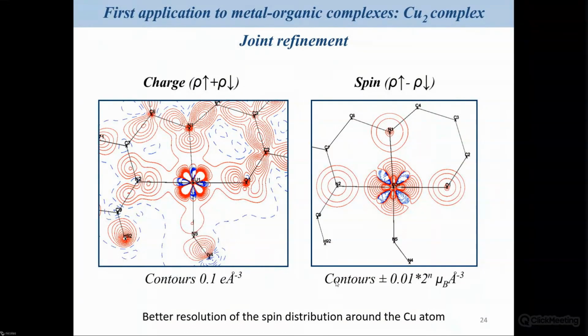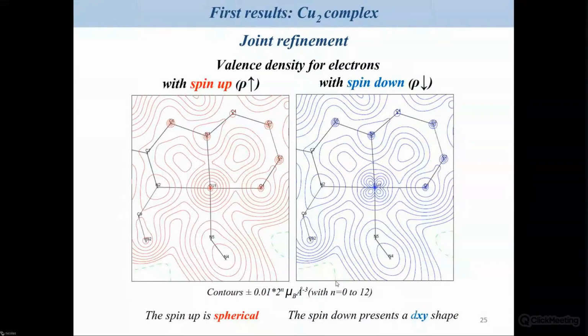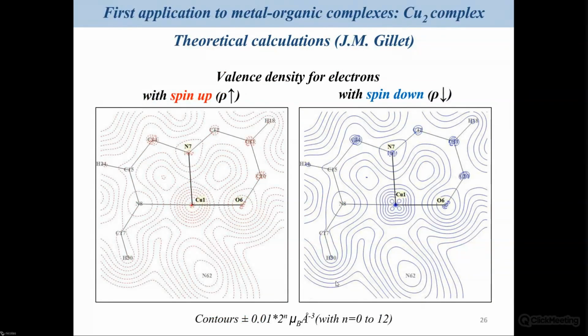But what is already interesting is, in fact, you have access to the spin up and spin down distributions separately, and you can plot them. So you can have maps showing only spin up on the left, or only spin down on the right, and you see that the distributions are not the same. And this is okay. This is what you can see there, because the spin up is completely spherical, but the spin down is not spherical. You see that you have a DXY shape, and if you compare that distribution to the same calculation made by Jean-Michel, you observe that they are completely comparable.